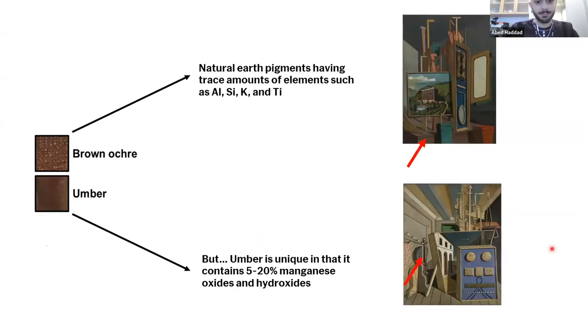So for the browns, de Chirico listed a variety of natural brown pigments, including burnt sienna, burnt and raw umber, and Van Dyke brown. Brown pigments are most often iron oxide species of varying compositions, which range in tonality depending on calcination. And Van Dyke brown and Cassel earth are humic earths rich in organic materials, which can be difficult to identify exclusively with something like XRF.